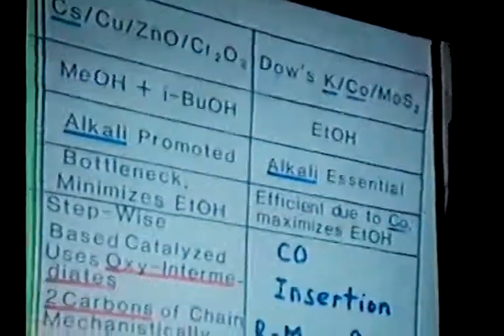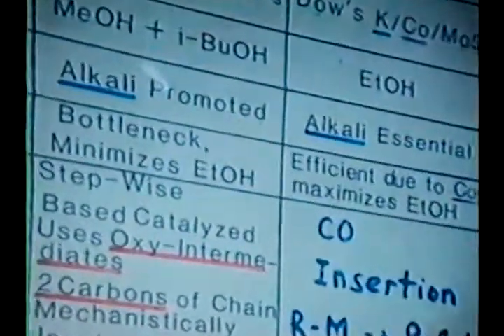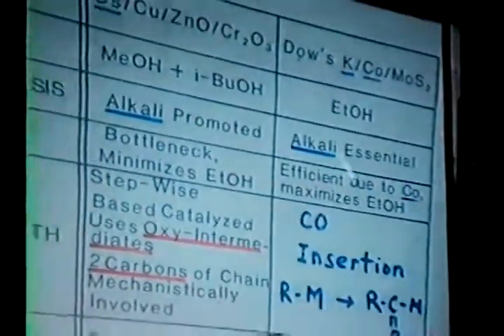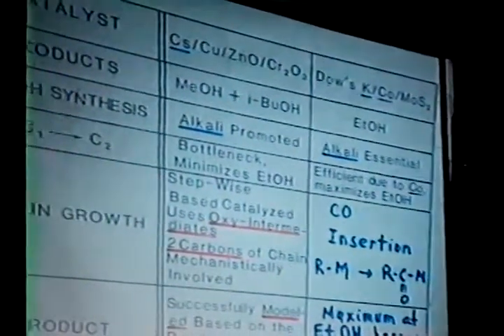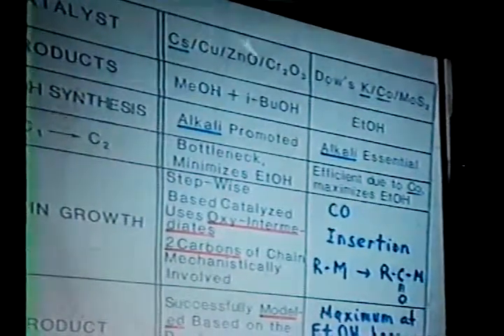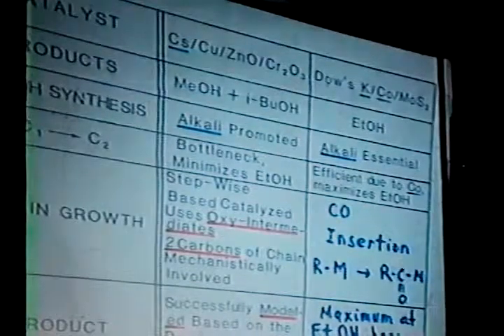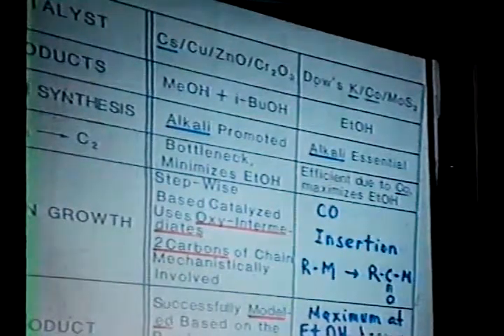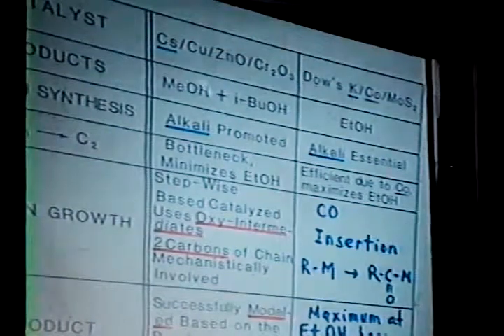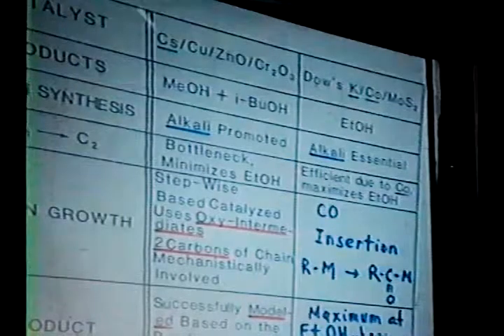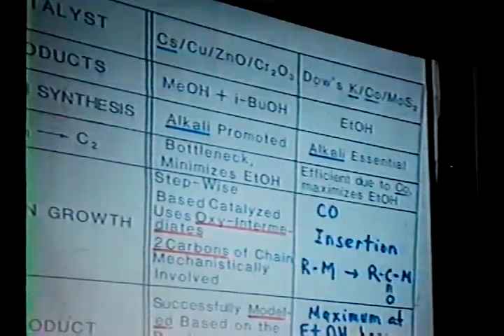Both methanol syntheses are alkali promoted or alkali essential. The alkali are essential in the Dow's catalyst. And here we already have a basic component, zinc oxide, which also promotes methanol synthesis by the formate mechanism, but by a far less efficient path than the alkali promoted one. And so the cesium has been kind of an unexpected benefit there, because people in the literature, including patent literature, say that you can't promote methanol with alkali unless you make higher alcohols.